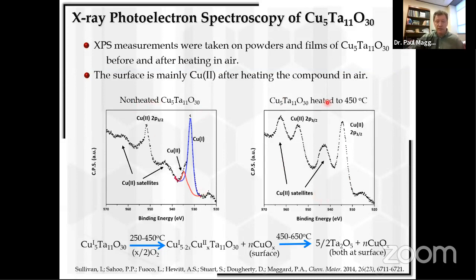And so this is non-heated, and this is heated to 450. And so if you balance the reaction, right, copper 51130 is all copper 1+. And as you heat it, you're driving out copper oxide islands at the surface. And so there's an oxidation taking place there at the surface. And then as well, internally, the copper 1 is being oxidized to copper 2 as well. Okay, until eventually you heat it to too high of a temperature, and then it's a complete decomposition.